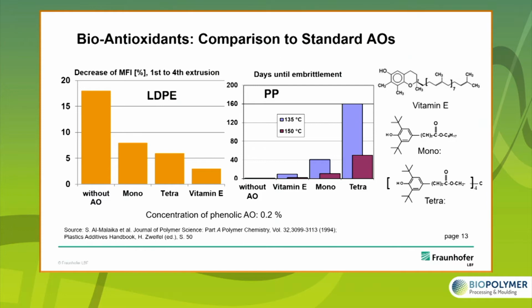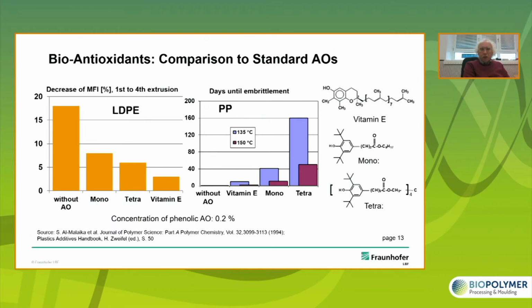The other side is of course the long-term heat stabilization. You see this on the example of PP on the right-hand side. Normally, you test under higher temperatures, here 135 degrees and 150 degrees in red. You see that without antioxidants, we see embrittlement within hours, not talking about days.